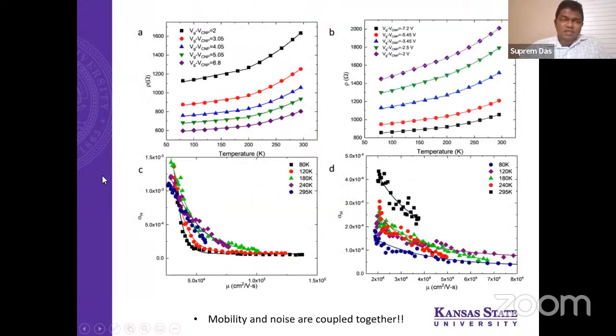So we did extensive measurements with temperature, resistivity versus the temperature, from which we calculated alpha, and also independently we calculated mobility, and we did see that they are very tightly correlated. So alpha and mu, you can see with temperature, they are very much correlated, and we have a functional dependence. If you look at our paper, we found some of the correlation from this plot.